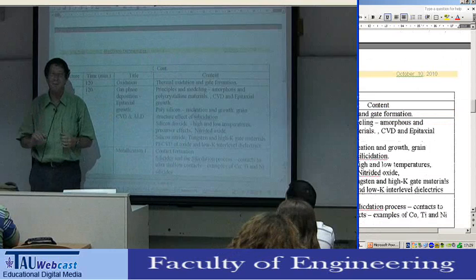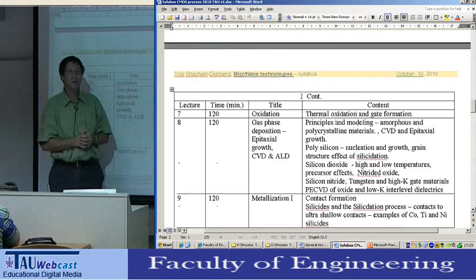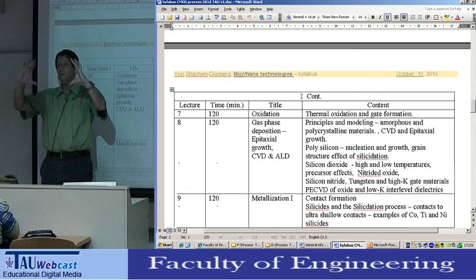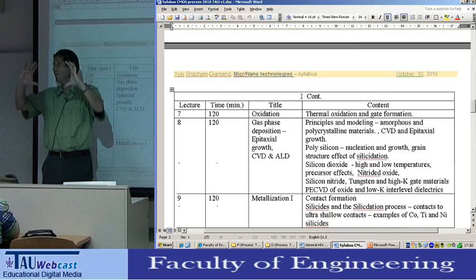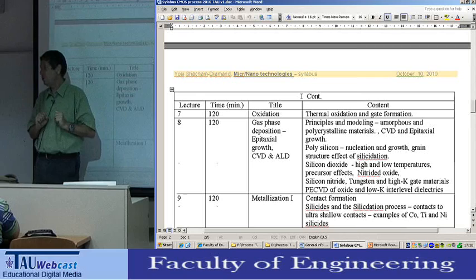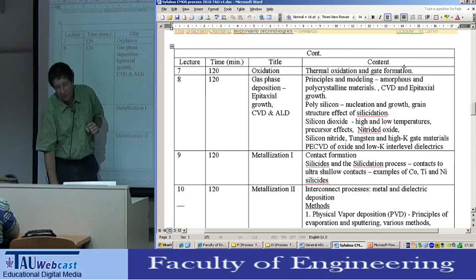I mean, sometimes it's very easy to heat, just put it in flame, but it's not a good idea because it's not controlled. Imagine that you take a silicon wafer with a diameter of 30 centimeters and I want it to go to 800 degrees plus minus 1 degree all over the wafer in 5 seconds. So this is what I'm going to teach you how to do or explain to you. Then oxidation. Thermal oxidation and gate formation.